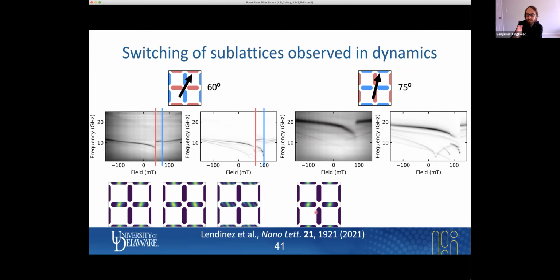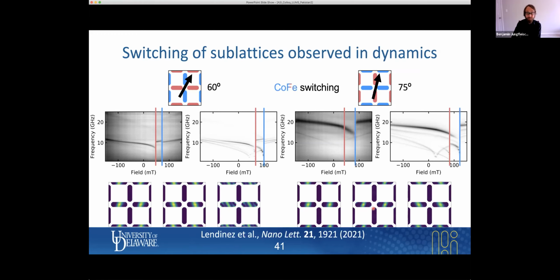Now let's increase the field up to the point when nickel iron switches. When the nickel iron switches, we see the formation of a higher order mode. It's not as visible as in the other bicomponent lattice, but nonetheless, we see that. And then when the cobalt iron switches, we see the change in the tilt in the magnetization oscillations. So the bottom line, the key message here, is that the switching of the vertical elements can be seen in the dynamics of the horizontal elements. And by changing the materials on the lattice sites and modifying the in-plane field angles, the dynamic behavior can be tuned.